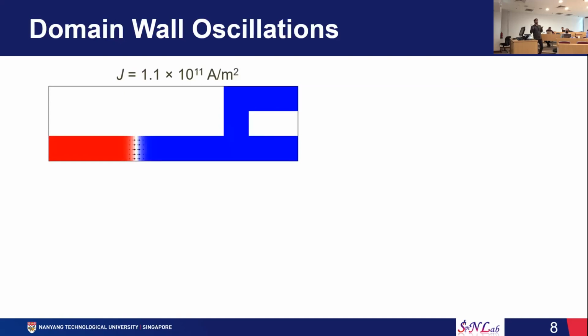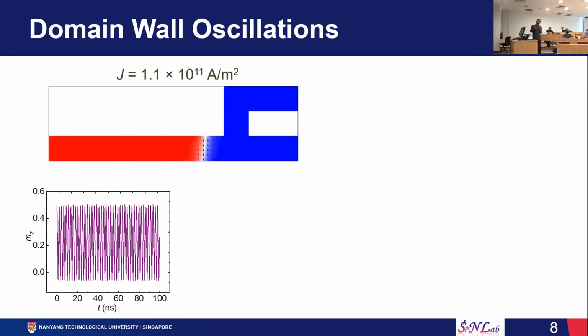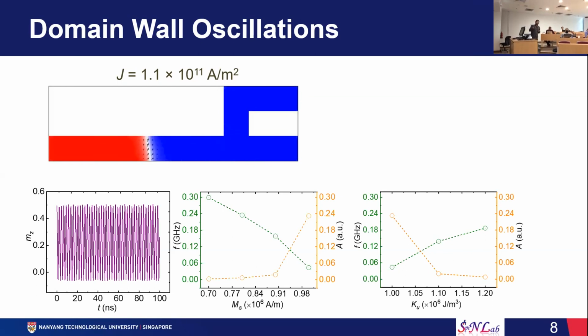Now, we have seen this damped type of oscillation. We have also explored domain-wall dynamics with this type of sustained oscillation for a certain current density, 1.1 × 10^11 ampere per square meter. You can see this sustained oscillation in this plot as well. We can tune the material and magnetic parameters like saturation magnetization and Ku, the anisotropy constant, to get this type of sustained oscillation. So it's a damped oscillation, and from that we can tune it so there is a continuous transition to sustained oscillation.